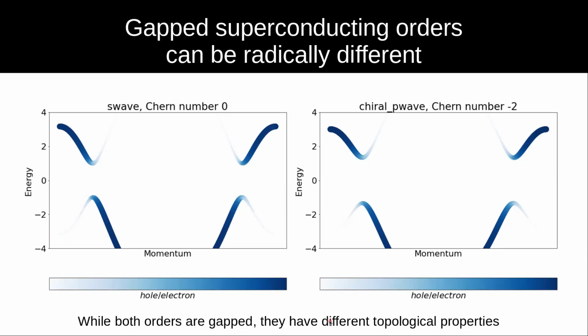Something very interesting is that you can have different superconducting orders that have very, very similar spectral properties. So here you can see, for example, the case of an electronic structure that has an S-wave superconducting order, non-zero everywhere in reciprocal space, and therefore opens up a gap in every single point in reciprocal space. And then here on the right, you have the example of a chiral p-wave order. So this is a superconducting order that has a strong dependence in momentum space. In particular, it has a winding number in reciprocal space. But then when you project it on the Fermi surface, it is capable of gapping the Fermi surface at every single point. Spectrally, these two superconducting gaps look the same.